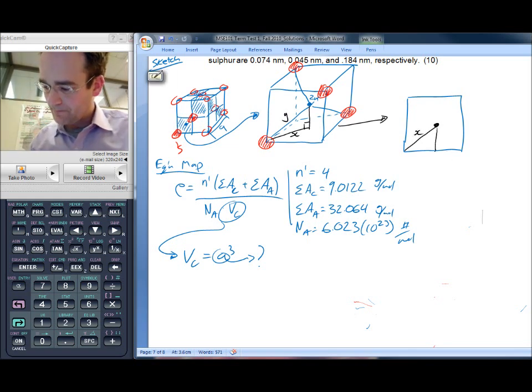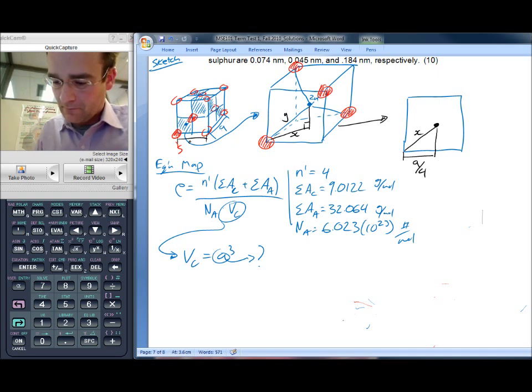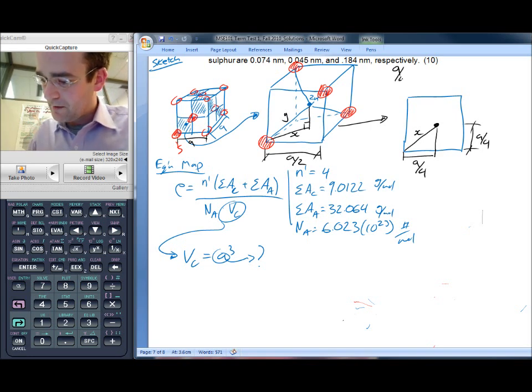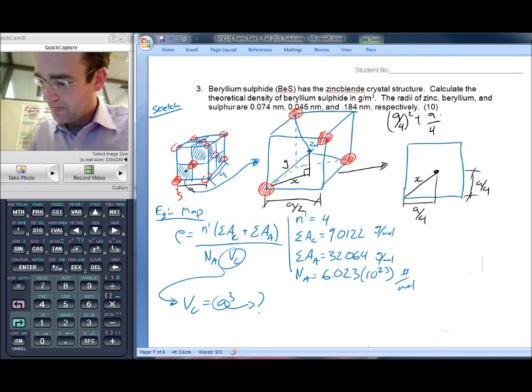Would cross over like this, or we can call that length X, the hypotenuse Y. And this would be X. So we can actually determine the length of X, because we know this to be A by 4. If the full length is A, half is A by 2. This is A by 4, as is this height here. So A by 4 squared plus A by 4 squared equals X squared, or X equals A by root 8.